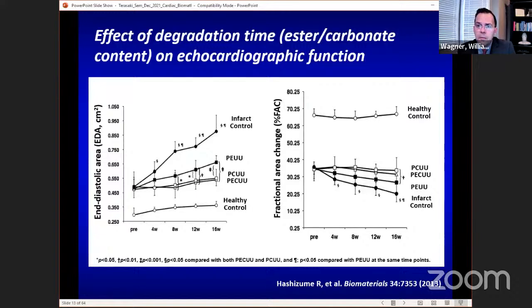So we looked at 3 different polyurethanes. The polyester, which is fast degrading relatively, polycarbonate, which was the slowest degrading, and a 50-50 molar blend of the 2 in the soft segments. And that was in between the 2 in degradation rates. And the answer that we were looking for became clear: the 2 slower degrading ones were equivalent statistically, and they were both better than the faster degrading patch. So you see here, end diastolic area, this is that rat model. The slower degrading patches do better than the faster degrading patch.